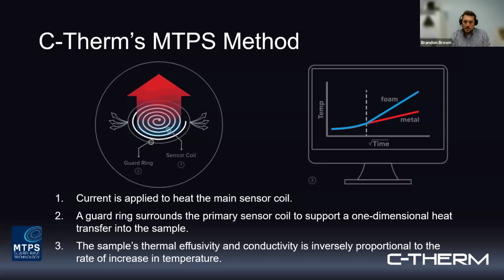The patented guard ring forces the heat flow to be in one direction. The sensor coil provides the main heat pulse into the sample and is simultaneously monitored as the temperature progresses. Generally, the slope of the temperature over the square root of time will quantify a sample's effusivity. Samples with high effusivity, such as metals, will show a lower temperature slope, while something like a foam will show a higher temperature slope.